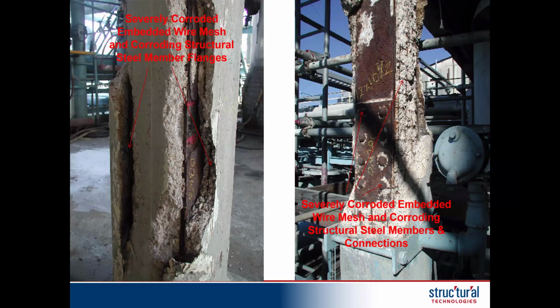And unfortunately, when I tapped those rivet heads, the rivet heads started popping off, and that obviously is a friction connection, a shear connection with the rivets in place. So that was a big problem, but obviously this was allowing the owner to make a risk assessment. Now the picture to the left is showing, yes, indeed, it had embedded wire, but it also had a lack of consolidation around it, a lot of honeycombing or rocks without cement paste. So that deteriorated very quickly, and you can see the flanges actually starting to corrode with that, and obviously not providing any fire protection.